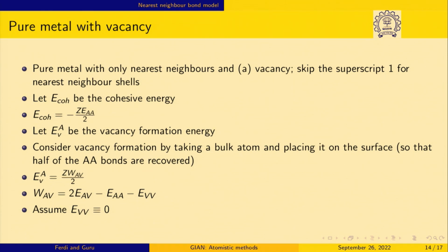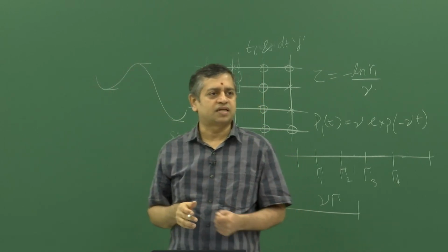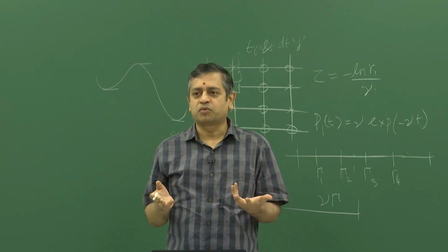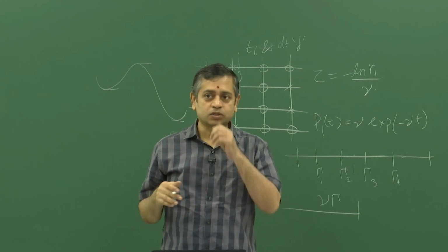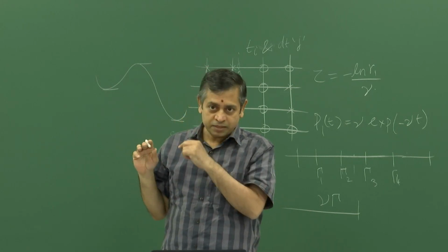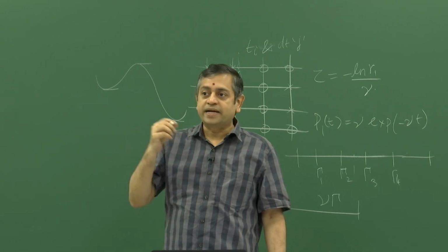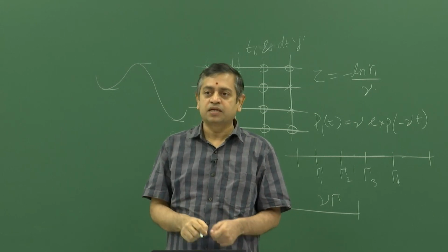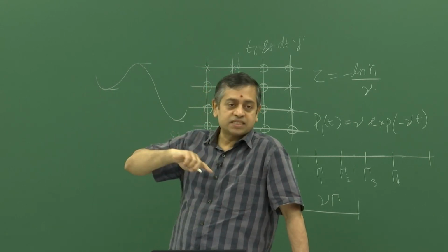So, you take a random direction and a crystal, cleave along that random direction, and count the number of broken bonds and attribute that as the surface energy, right. These kind of broken bond models are common, and here we are using one such broken bond model to identify the parameters associated with the system. In that paper those parameters are also given, and this calculation is given as an appendix.